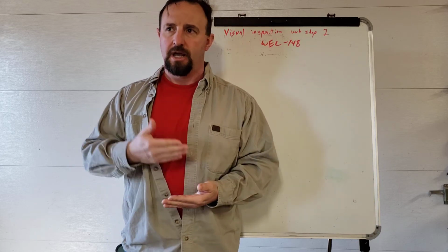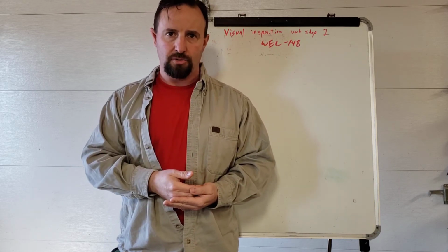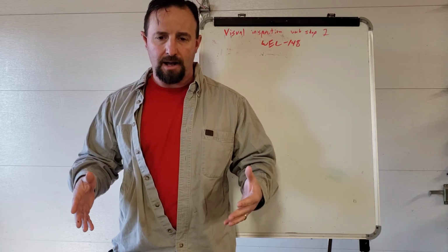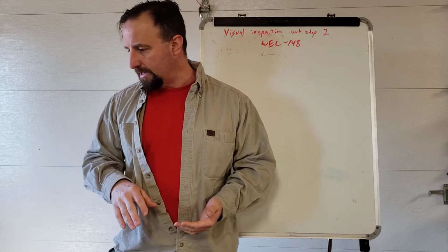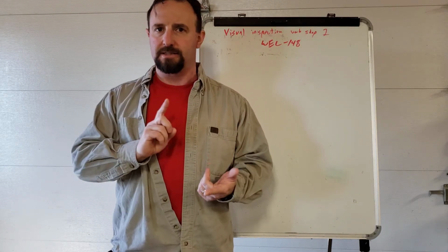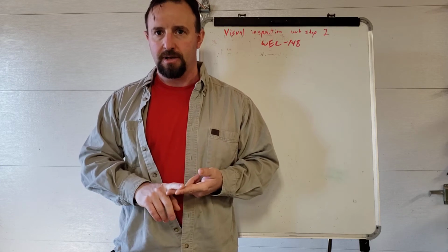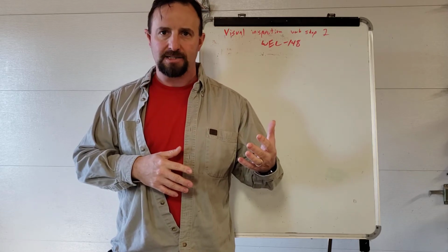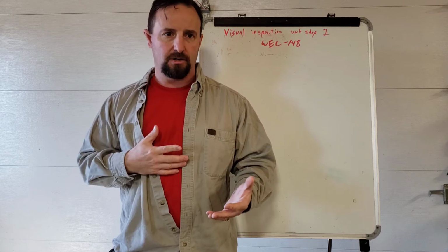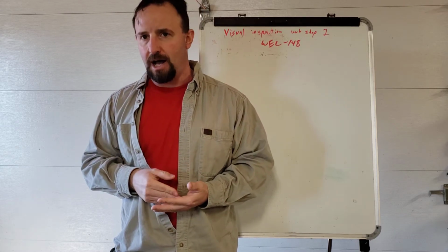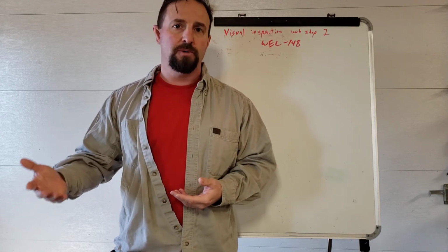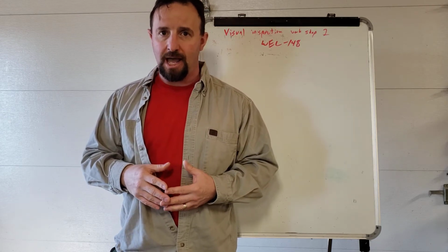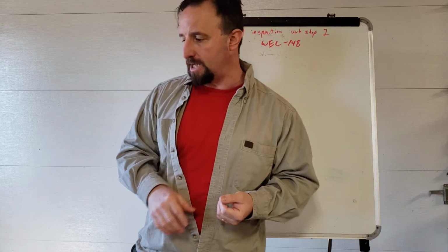Examples of metallic inclusions. If you get iron dust inside an aluminum weld, it'll break. Another one we're going to be talking about here in just a little bit is tungsten. Get to that when that slide comes up. But anything that's in that weld that is not base metal, that is not weld metal, is an inclusion. If it's a gas bubble, it's a gaseous inclusion. If it's sand, if it's dirt that fell down inside the weld, rust, paint that didn't burn out, all these are inclusions. If it's the wrong type of metal from some other form of contamination, in aluminum especially, if aluminum gets contaminated with steel, it will crack, it'll cause you nothing but issues. And so you can have metallic inclusions on top of your non-metallic inclusions.